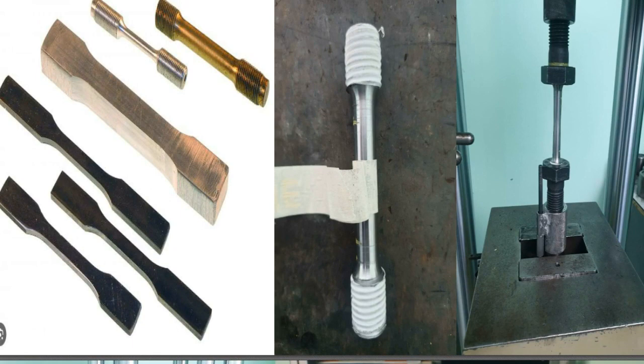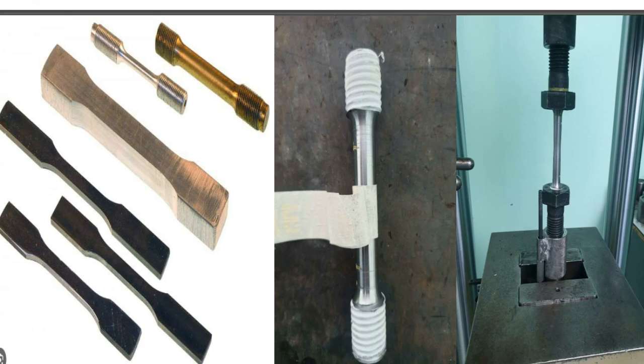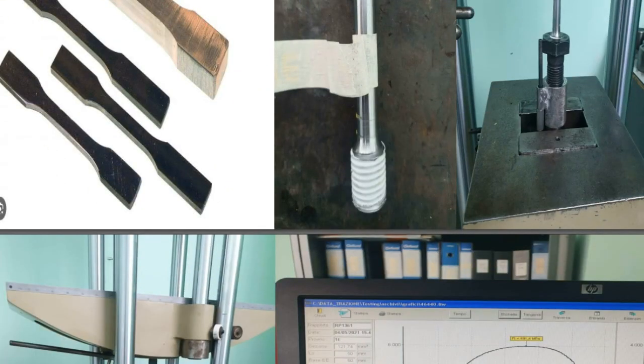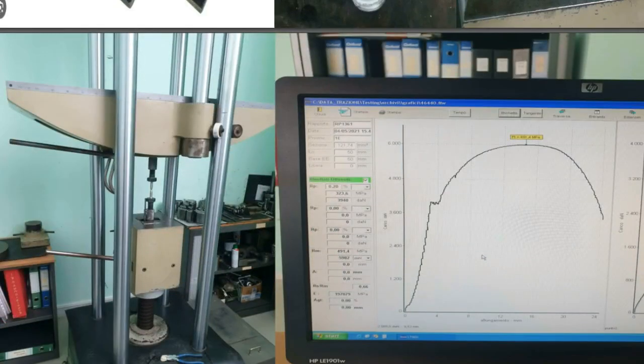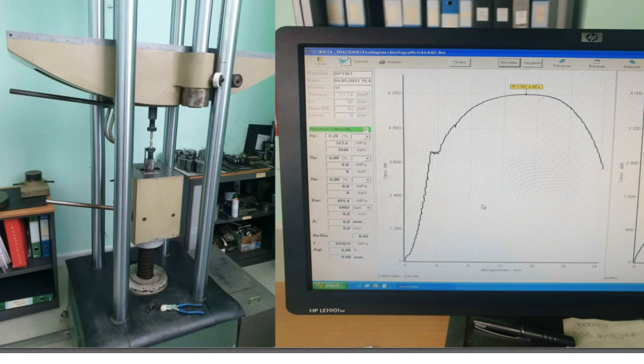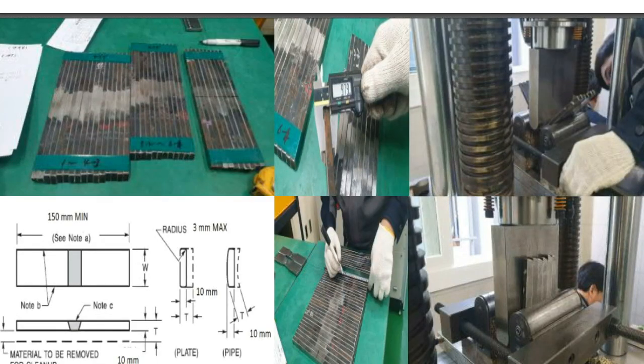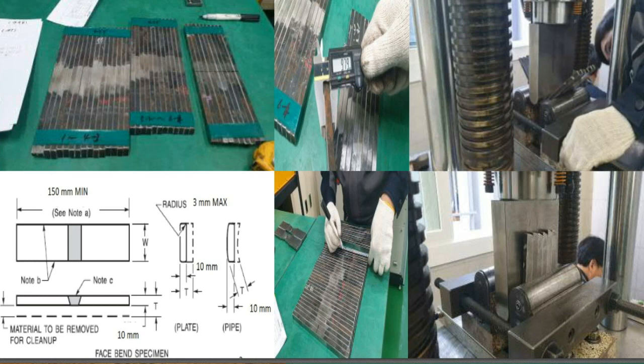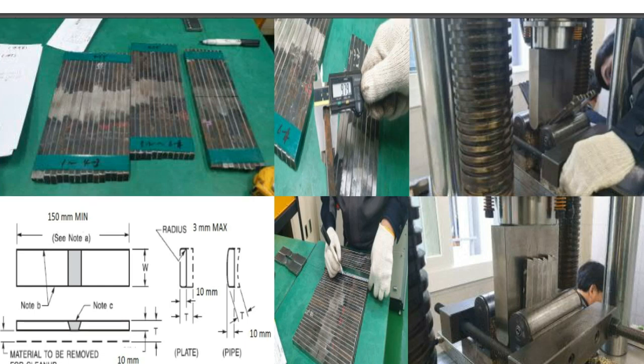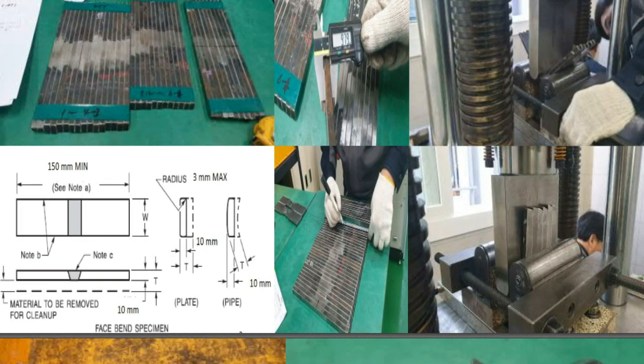And after welding, you need to do the tensile test. Two sets of tensile tests using a tensile machine, like this, with this kind of specimen. And you can see the tensile graph, the stress and strain graph, and figure out the ultimate tensile strength and yield strength. And after the tensile test, you do the bend test like this: face bend test, side bend test, and root bend test. Four sets, depending on the thickness.